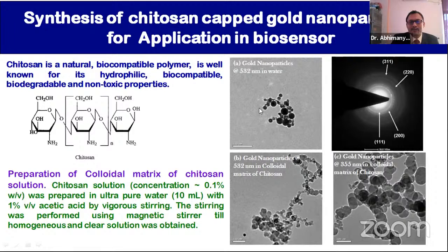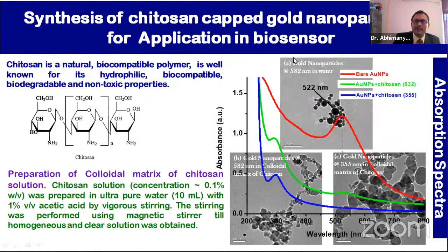This is the nanoparticle produced in water, and this is the gold nanoparticle produced in chitosan matrix. This is the absorption of bare gold nanoparticle, and this is the capped chitosan gold nanoparticle. From this we see that the surface plasmon resonance peak is reduced when capping occurs.